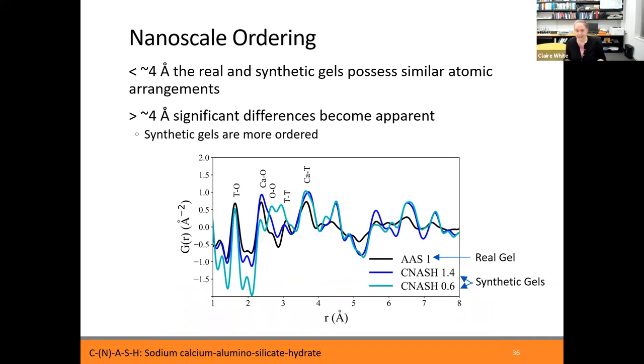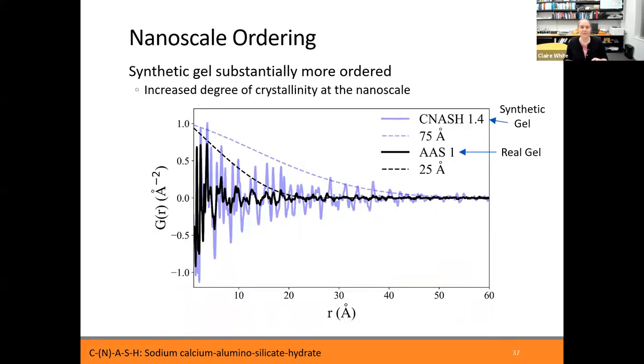Very much lastly, we're going to look at nanoscale ordering of these gels. So I've plotted out to a lot further in R space, in real space, for the pair distribution function. And you can see how the correlations, these atom-atom distances, die off a lot more quickly for this dark sample that's denoted here as AAS compared to the purple sample. There's a difference between these two.